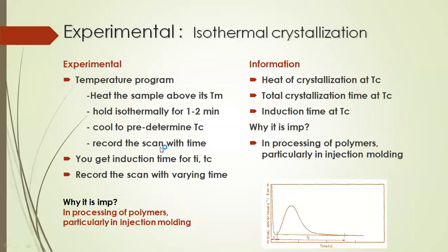Okay. Now, second is isothermal. Isothermal means, as the name indicates, with respect to time. Here, you heat the sample above its melting temperature and hold it there for 1 or 2 minutes to completely melt it. Then cool it to a predetermined crystallization temperature and record the scan with respect to time. What information do you get? You get heat of crystallization, total crystallization time, and induction time of crystallization. Induction time means the time at which your crystallization starts and the time at which it completes.